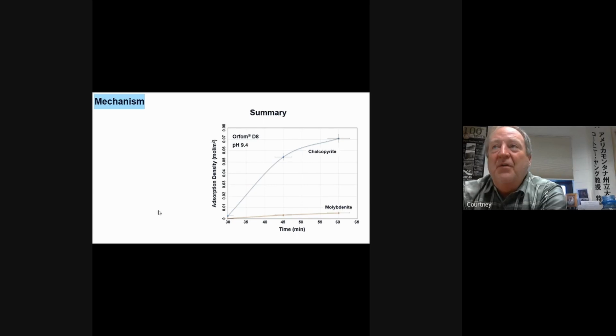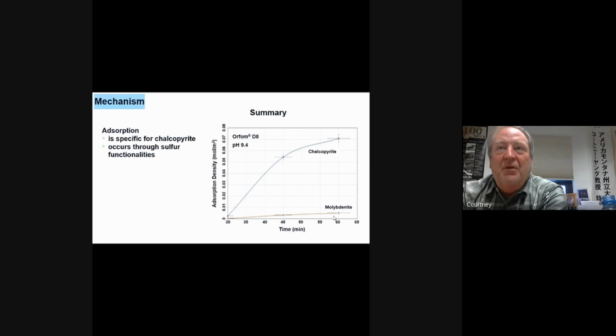So the other thing that we did is we took a look at, can we try to measure an adsorption density of Orfom D8 on chalcopyrite and on molybdenite? And what we're able to see here is that we get significant adsorption on the chalcopyrite, but very little adsorption on the moly. So if you're going to get depression action, it's going to happen with the chalcopyrite and not with the moly.